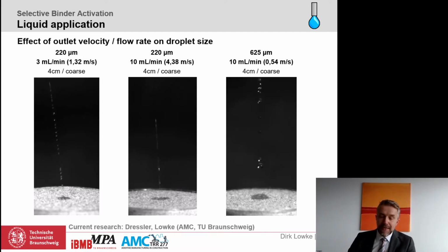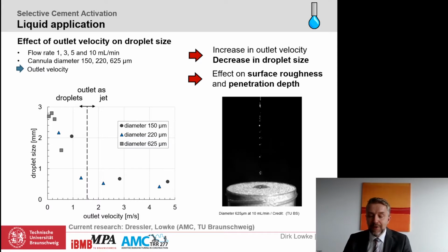But if you now express the flow rate and the nozzle diameter as a flow velocity, we can see that there's a functional relationship between flow velocity and droplet size. With increasing flow velocity, we can see a decreasing droplet size. Furthermore, we can also identify a flow velocity at which there is a transition from a droplet shape to a continuous water jet, in our case here, at 1.5 meters per second.